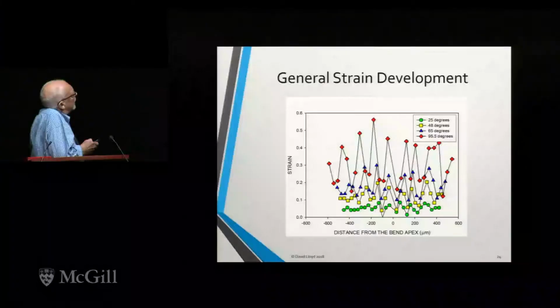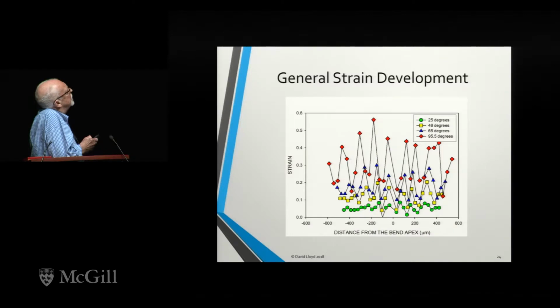The other thing that strikes you is that localization actually starts fairly early on. Here's an example where we've got this region where there's a localized strain, and then essentially it grows and grows.